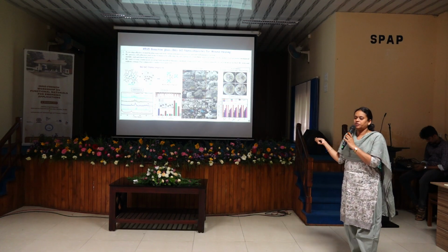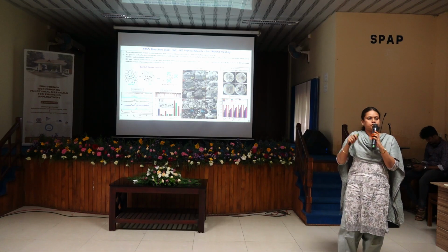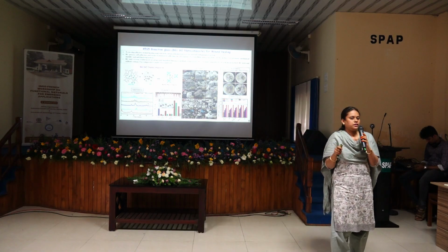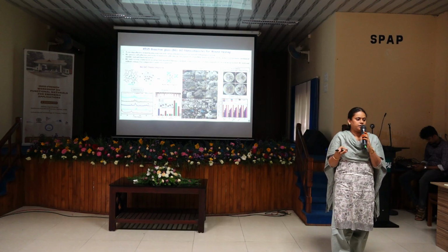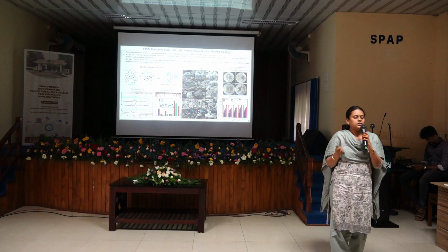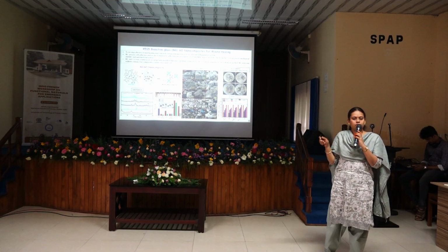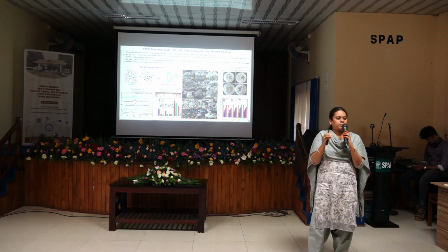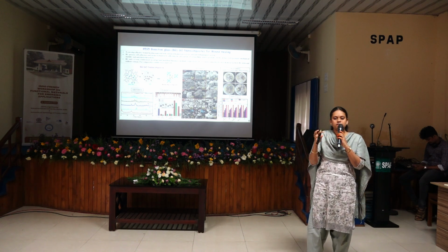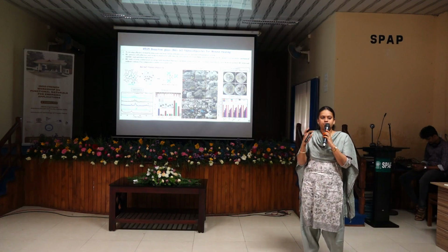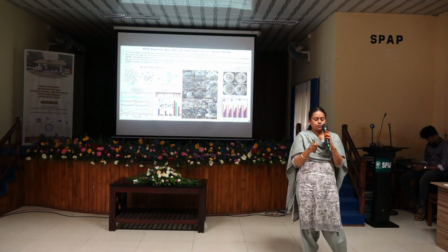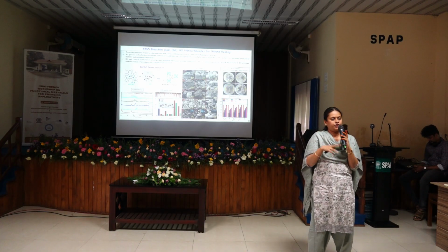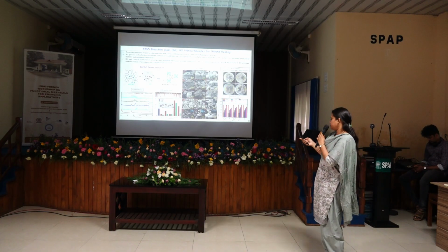Here I have to mention that bioglass with sodium and without sodium was synthesized, because as I said earlier, bioglass contains silica, calcium, phosphorus and sodium. The sodium in the bioglass may have a negative impact on wound healing, as it will lyse the blood. It will rupture the blood cells. So I have intended to work on both sodium-free and sodium-containing bioglass.